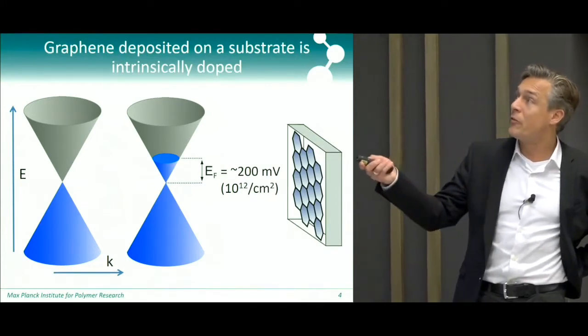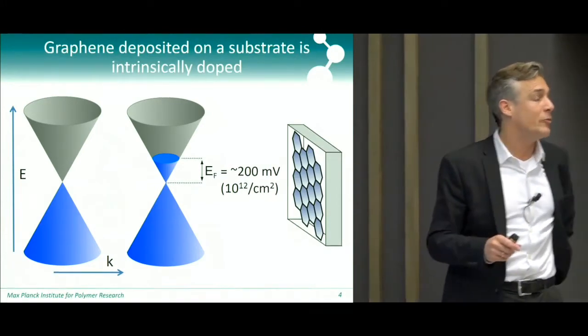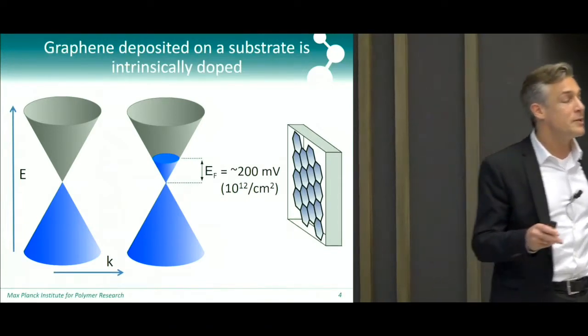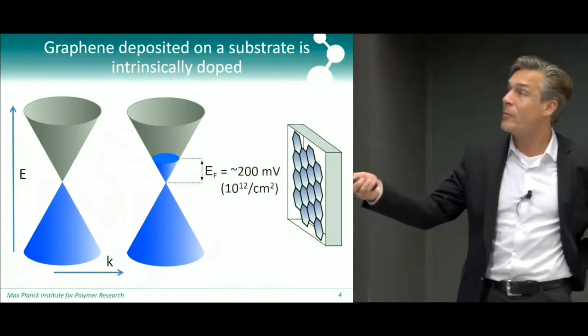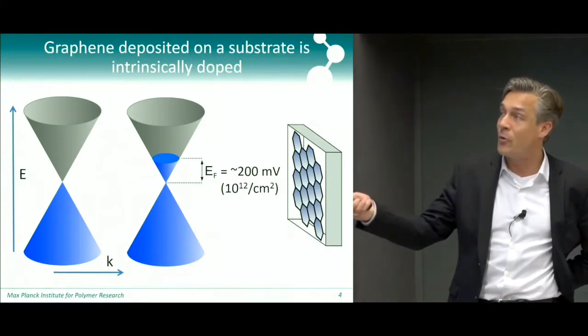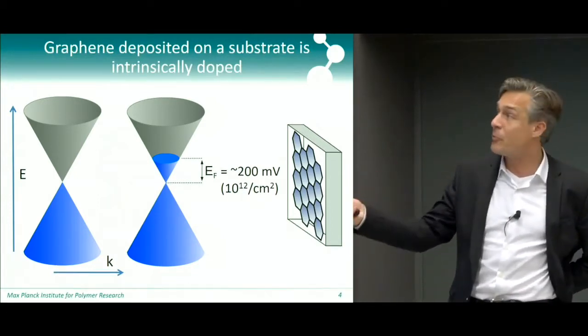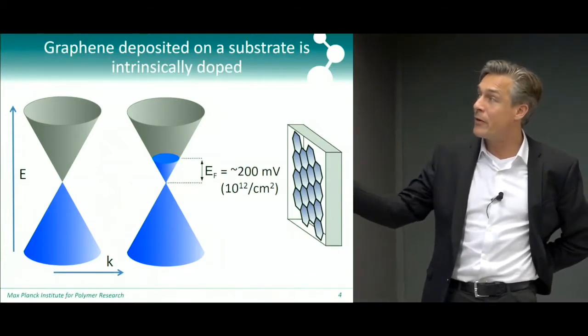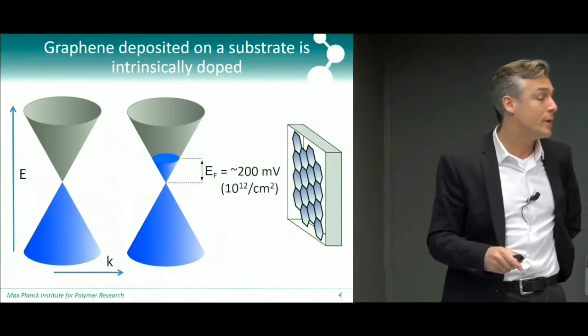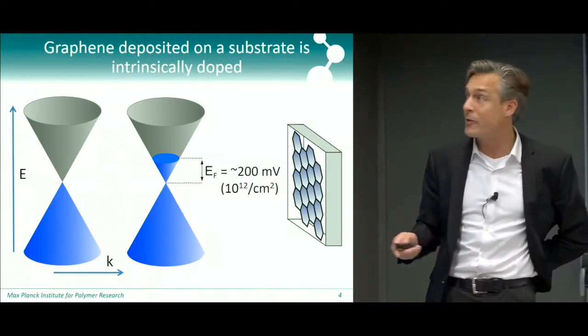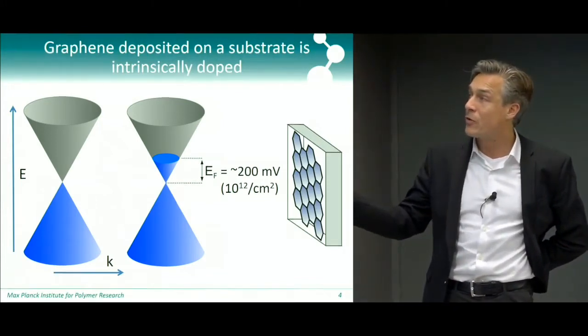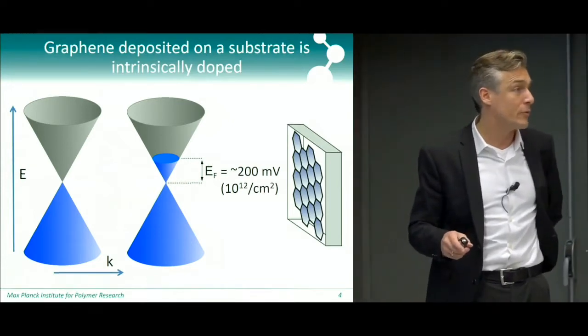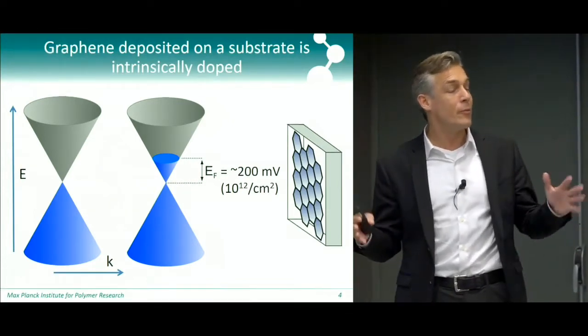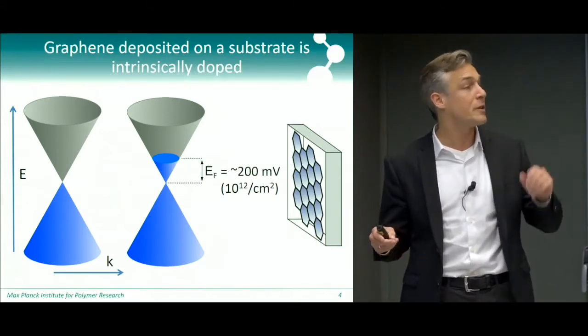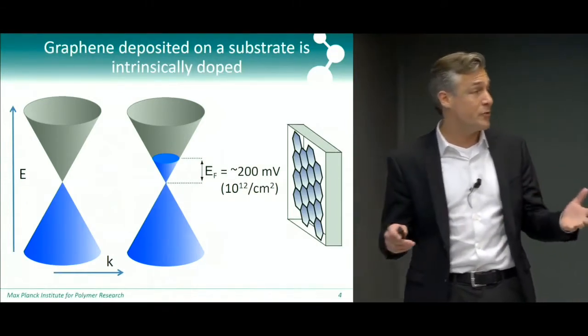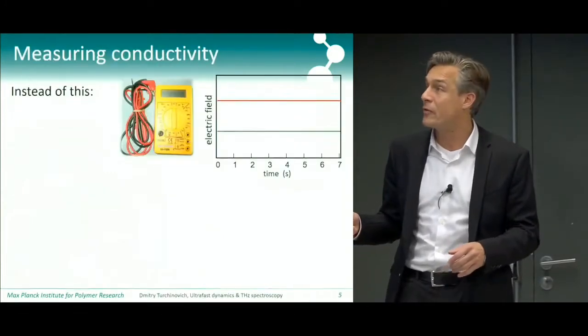Now, if you put graphene on, say, a silicon dioxide substrate, one thing you have to realize is that it gets doped. And so the Fermi level, which was originally at the Dirac point for suspended graphene, for supported graphene, you actually dope it with about 10 to the 12 dopants, electrons or holes, per square centimeter, corresponding to a Fermi energy of about 200 millivolt. And this means that graphene, when you put it on a substrate, is intrinsically conductive. And this is what we're interested in. We're interested in the conductivity of graphene.